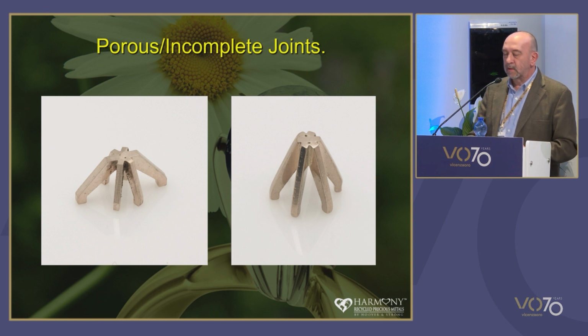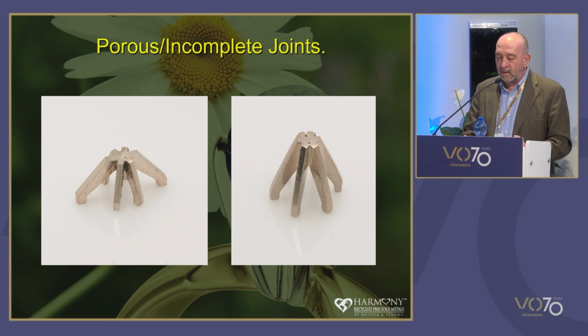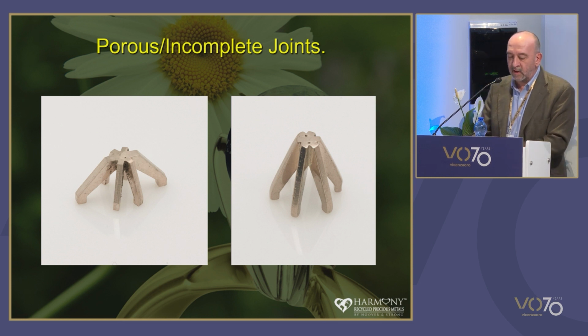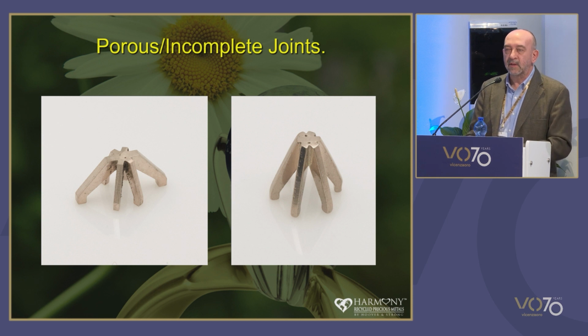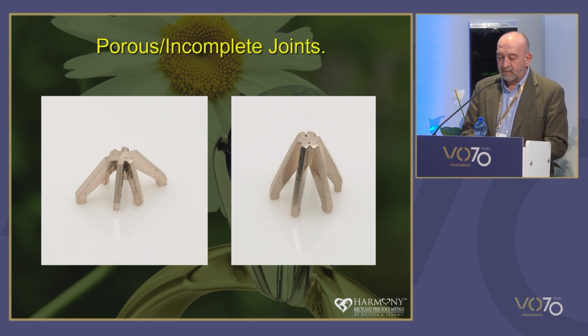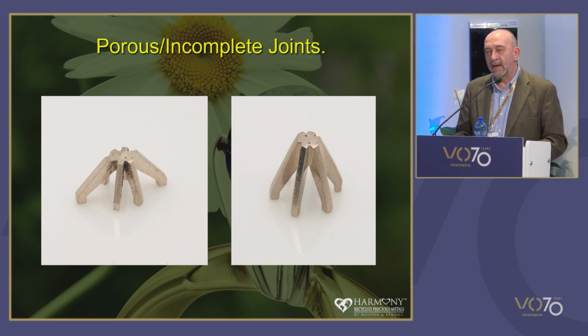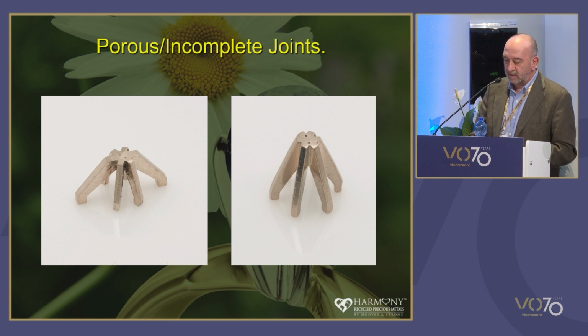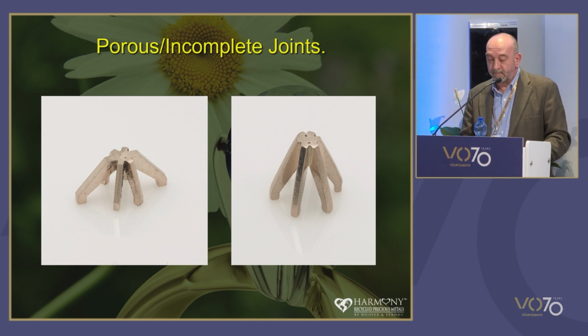Initially, the solder was blamed, and the investigations all focused into the area of the solder to try and identify this problem and then to try and eliminate it. And after starting this study, the type of defect started to occur in several other head-shank combinations using different solders. So it became obvious this investigation needed to go deeper.